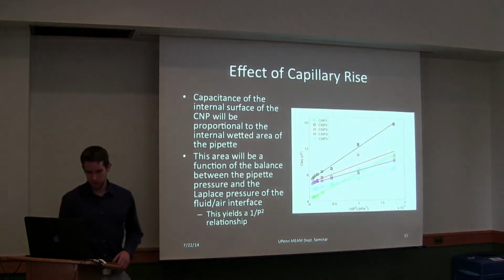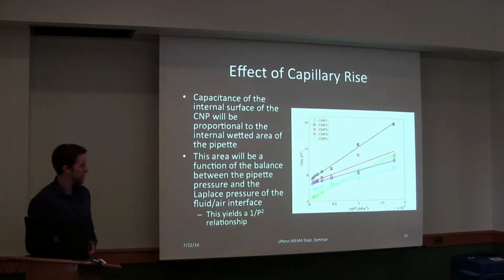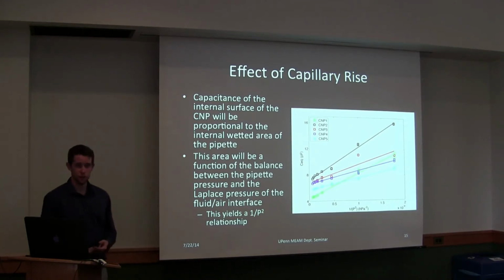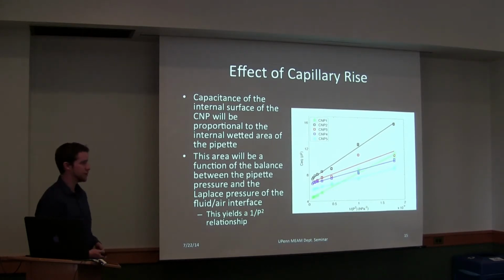We can also look at the effect of capillary rise in the pipettes to characterize what the effect of fluid in the pipette is going to be. So in this case, the capacitance of the internal surface will be proportional to the internal wetted area of the pipette. And this internal wetted area is a function of the balance between any pressure you're applying to the pipette and the Laplace pressure. And because the tip is conical, this yields a 1 over pressure squared relationship.